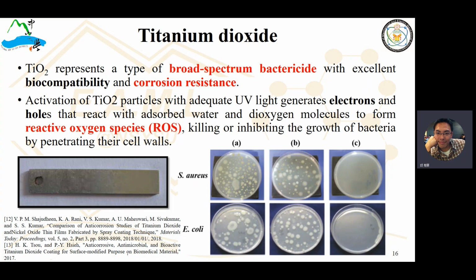And the other material I'm going to introduce is titanium dioxide, which represents a type of broad-spectrum bactericide with excellent biocompatibility and corrosion resistance. Okay, and the activation of TiO2, the titanium dioxide particles, with UV light generates electrons and holes that react with the adsorbed water and dioxygen molecules to form ROS, the reactive oxygen species, that can kill and inhibit the growth of bacteria.